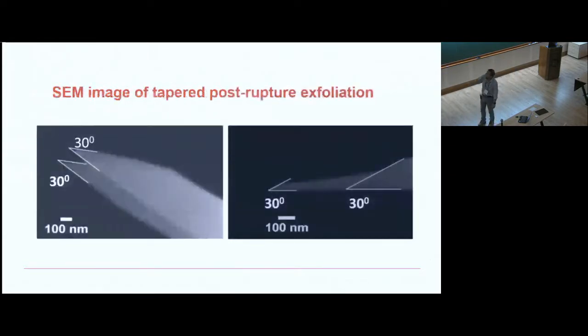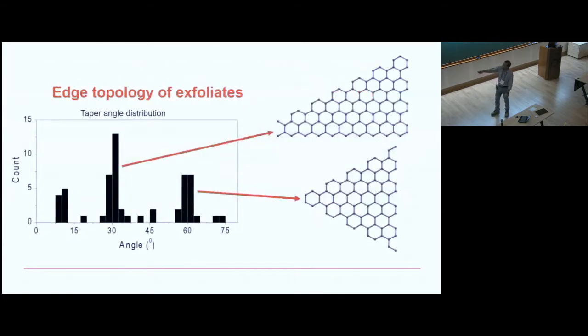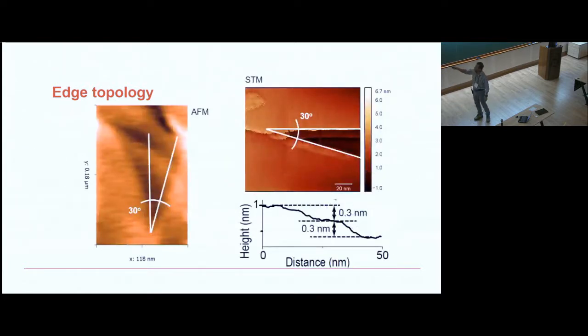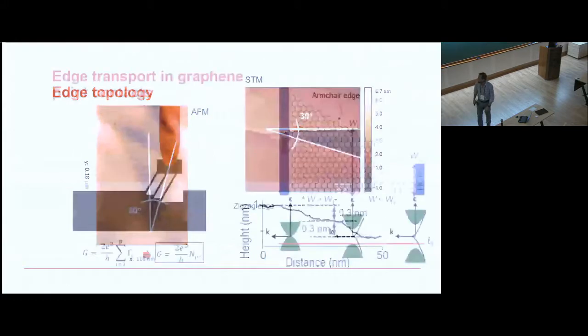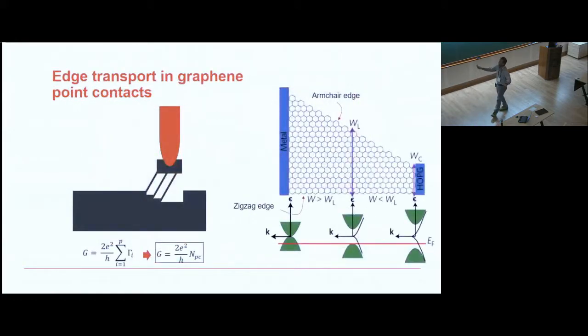And what is interesting is that if you look at the tips, this is about 30 degrees, which is very interesting because if you have got a 30-degree angle of the taper, it means that one edge of the tip or the contact is zigzag and the other edge is armchair. Armchair is semiconducting, zigzag is exactly perfectly metallic. And this is what our STM measurements also show, that we are making single layer graphene at an angle of 30 degrees of the apex. So that means one of the edges is a perfectly conducting edge. Okay. So this is the overall picture, what's happening.